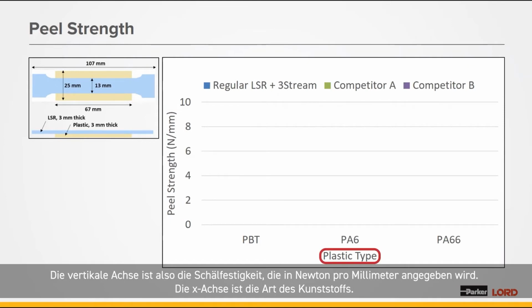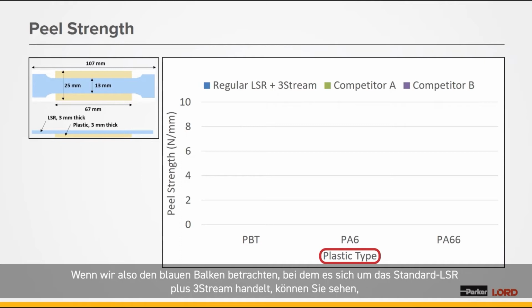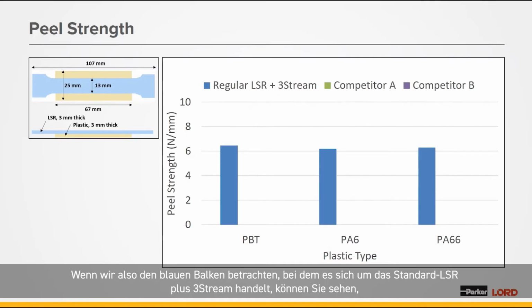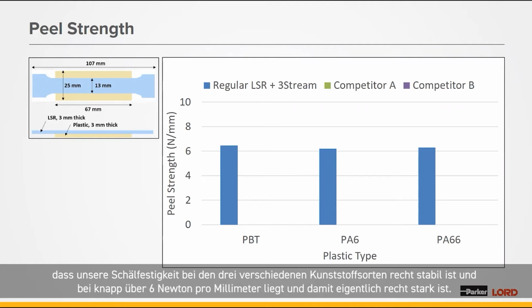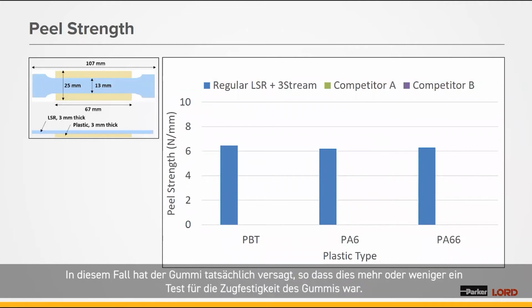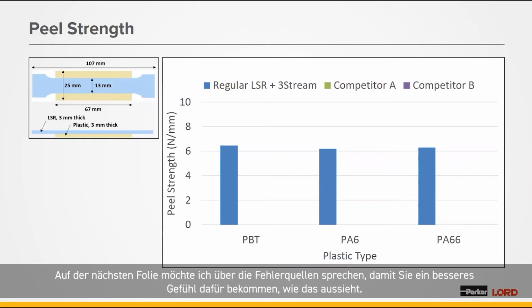The x-axis is the type of plastic. So when we look at the blue bar, which is the regular LSR plus 3-stream, you can see we're pretty stable across the 3 different grades of plastics. Our peel strength was just above 6 newtons per millimeter, which is actually quite strong. In this case, the rubber was actually failing, so this more or less measured the strength of the rubber. And I'm going to talk about failure mode on the next slide so you can get a better feel for what that looks like.